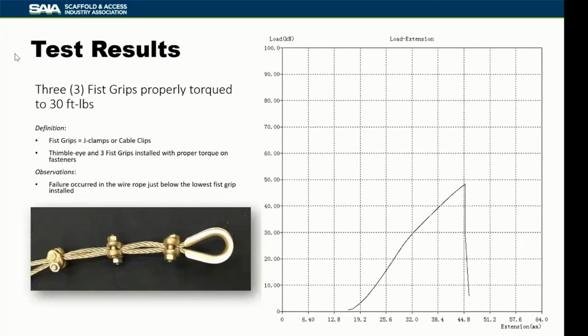If we go to our fist grips that are properly torqued, and again, it shows 30 foot-pounds here. I believe the proper torque is actually 35, and that's what was actually used. I just had an error in my presentation. This was set up with 3 fist grips, which is what is recommended, and spacing them roughly 3 inches, or a lot of people just use the width of their hand as to how far apart the fist grips should be spaced.